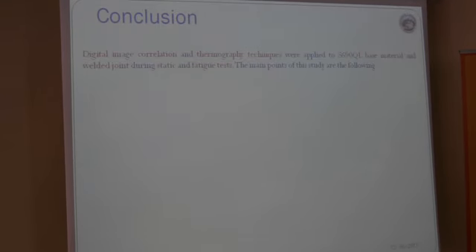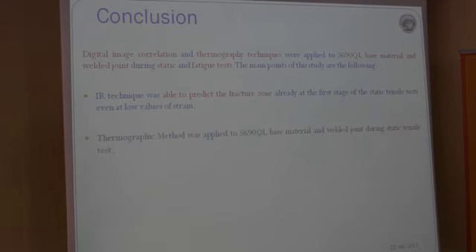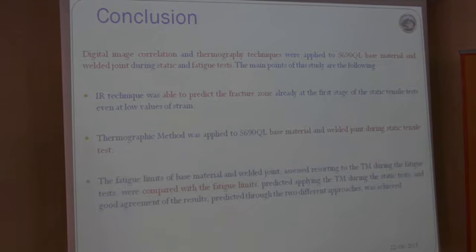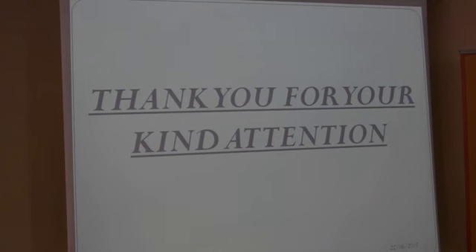In conclusion, the digital image correlation and thermographic technique was applied to this steel, on base material and welded joint, during the static and fatigue test. We can see that the IR technique was able to predict the failure zone, the fracture zone, in the first stage. The thermographic methodology was applied to a new steel, new for this methodology, for base material and welded joint during the static test. And we have compared the results of the fatigue limit from the static test and the fatigue test. Thank you for your kind attention.